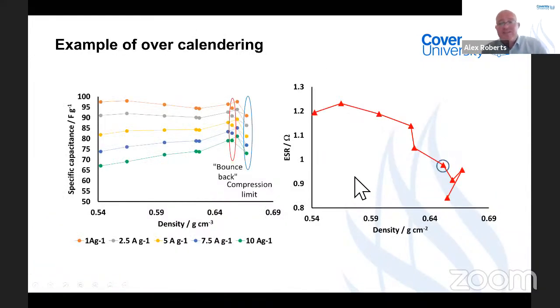So again, to show you an example of this, again in supercaps, we can see a study that I was doing on just looking at the effects of calendaring. As the density is increased on a very, very porous activated carbon, you can see I reach a point here. It doesn't really matter about the specific capacitance and the different rates. You can see what's happening here. We're bouncing back and we're losing some of this density. And you can see down here in the ESR measurements, everything starts to go wrong. So if I made cells beyond this circled point here, I would have problems. And that is what I found from the study.